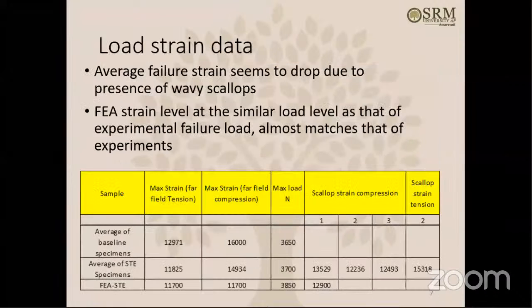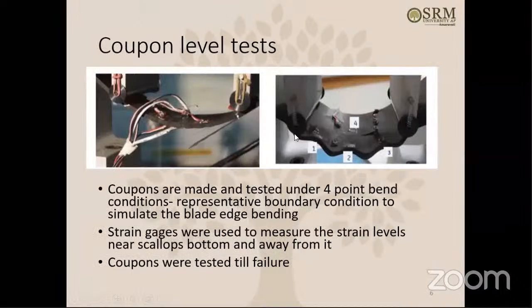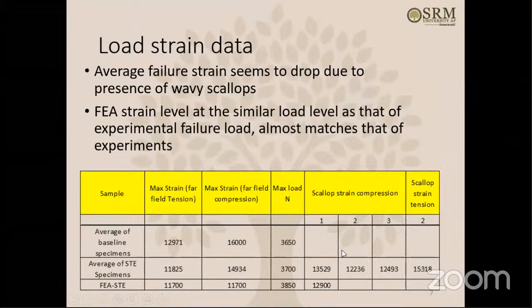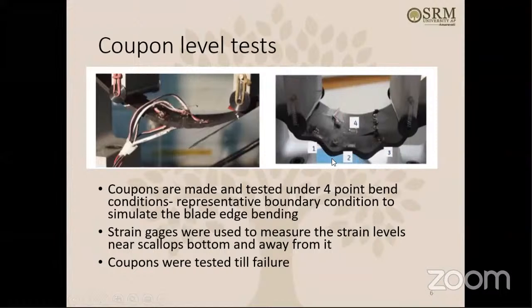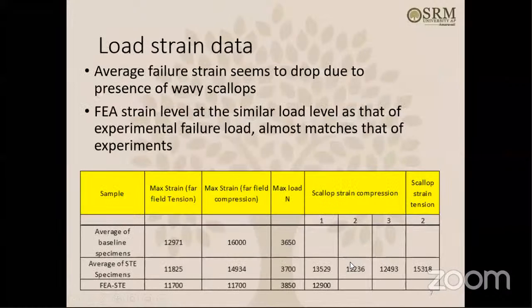So what does it give us? As you can see, the maximum strain far field tension strain gauge is showing these readings, then the far field compression strain gauge, and then the scallop strain gauge. Scallop means one wavy feature: one wavy feature, second, third, so 3 scallops, like 1, 2, 3. These are the strain levels, the scallop strain in tension and the scallop strain in compression. When you bend the coupon like this, the bottom side of the coupon will be under tension and the top side will be under compression. That's what it's showing here, the compression strain gauges and the tension strain gauges.